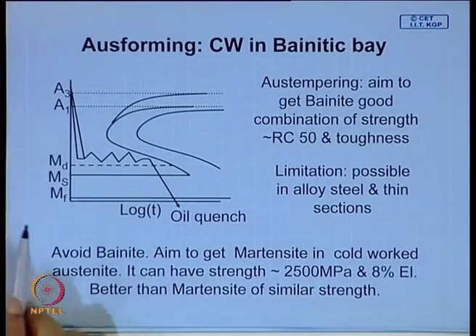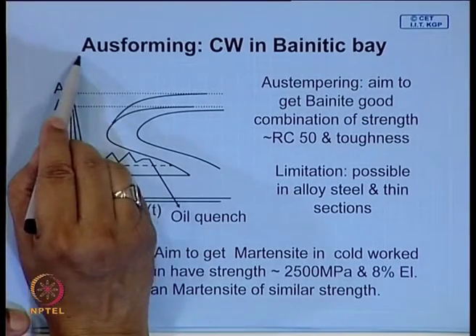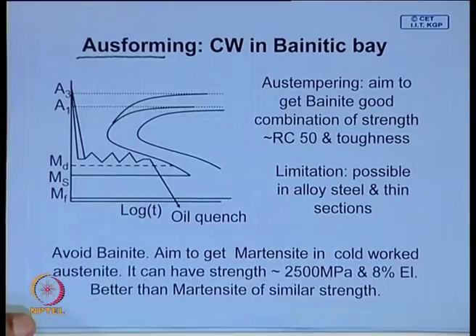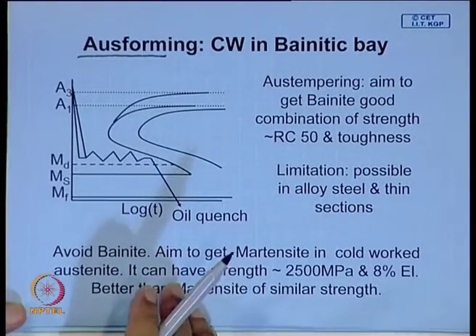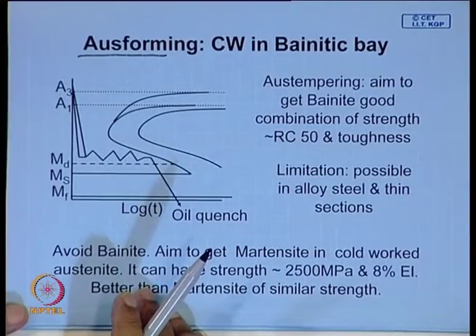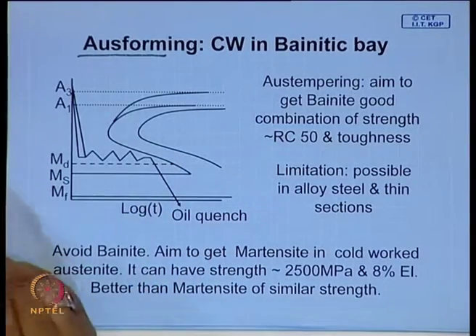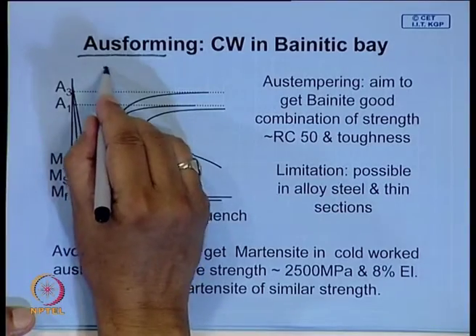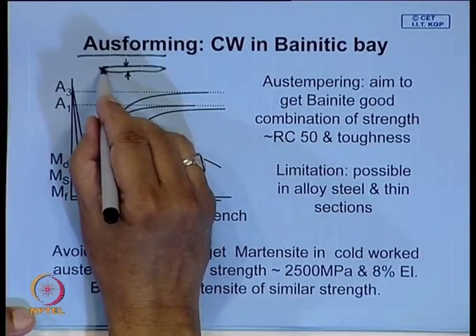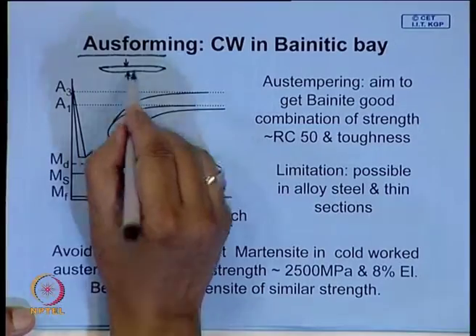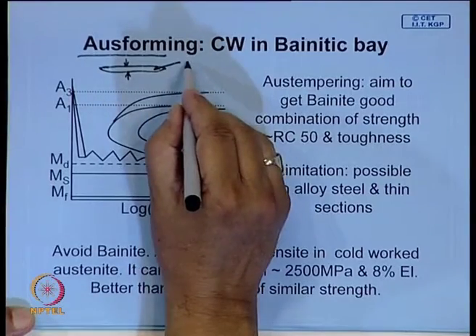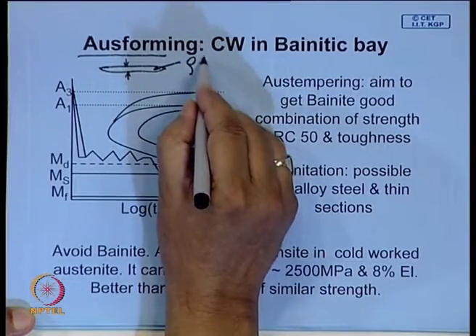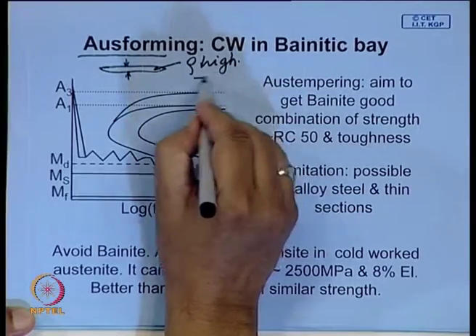Now, let us look at another special forming process called ausforming. Now, during microalloyed steel, what we found out is if you work austenite at a lower temperature, that austenite will not recrystallize, and these austenite grains, if you deform in one direction, become highly elongated. So, at least in this one direction they become extremely small in dimension, and they do not recrystallize. So, they will also have high dislocation density. So, rho will be high, dislocation density is high.